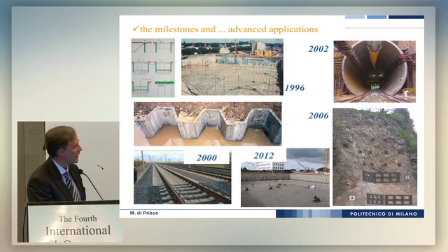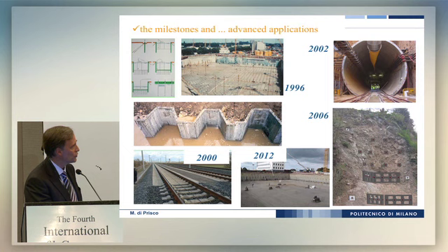There was a huge pressure because there was a huge difference of water pressure, if you like, because the phreatic water was at about 16 meter of pressure height. And he tried to use just fibre-reinforced concrete without any pump, and it created a very good slab. And when he removed all the water, no cracks could be seen. And so this was probably the most important application we had at that time.